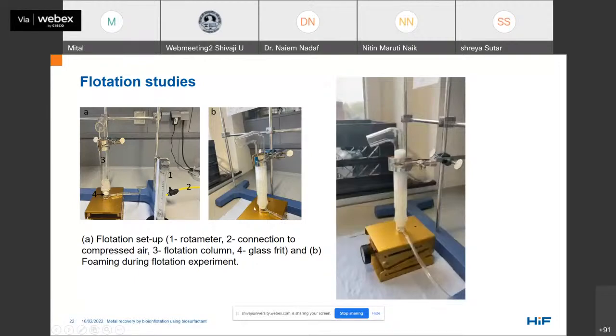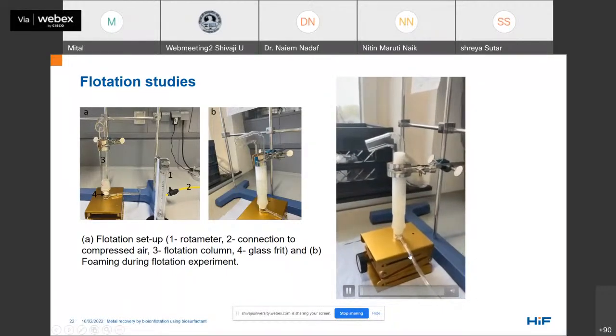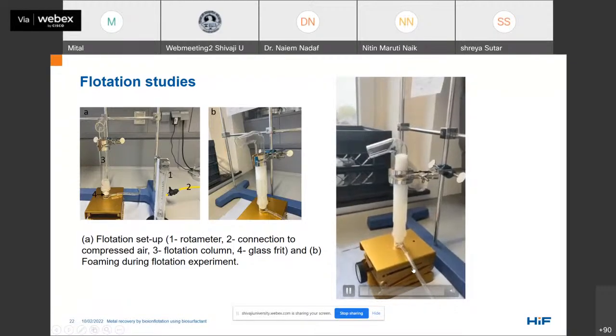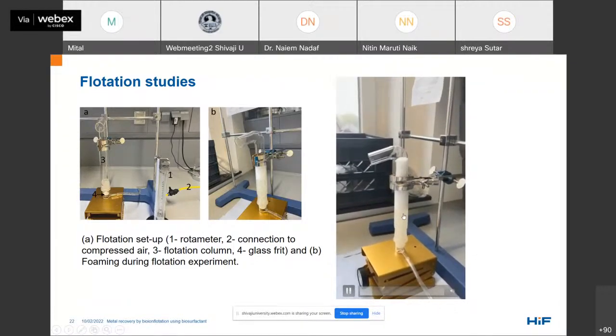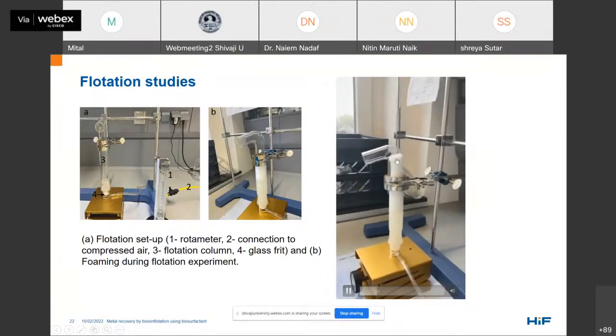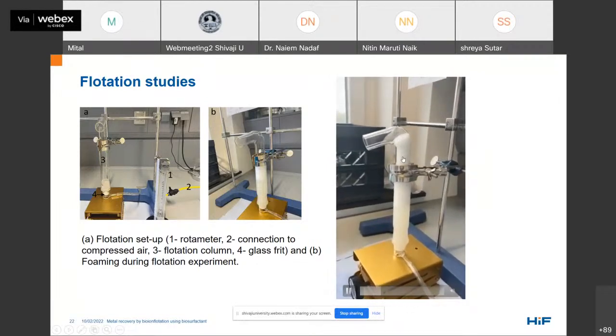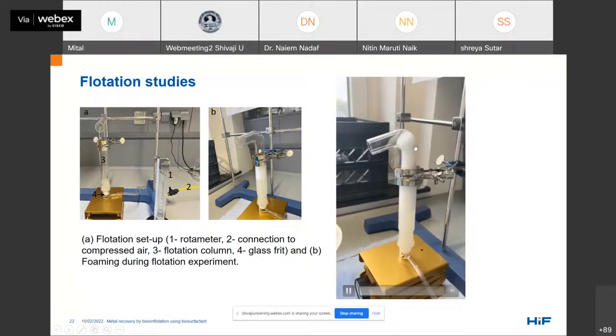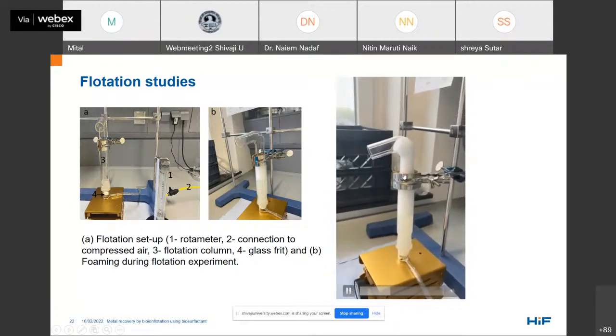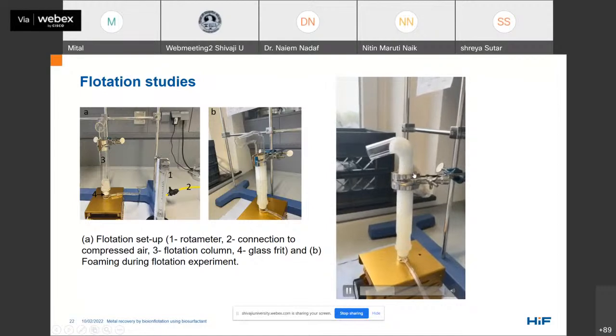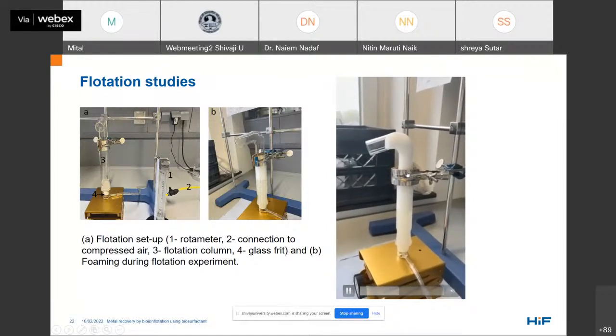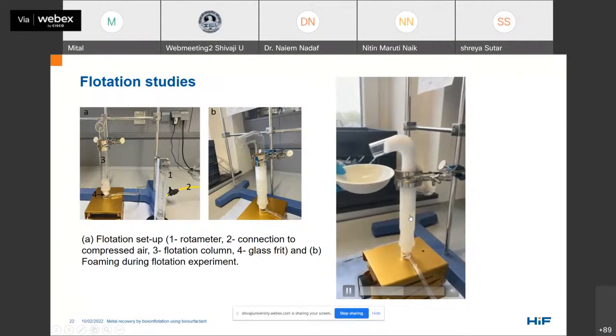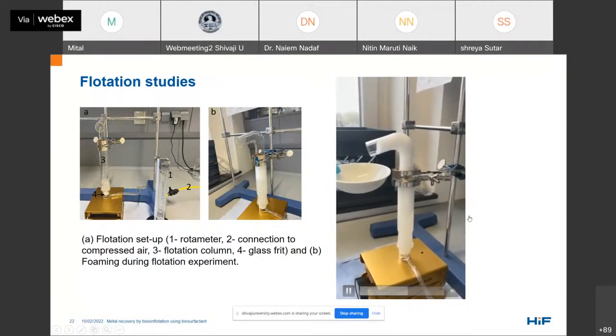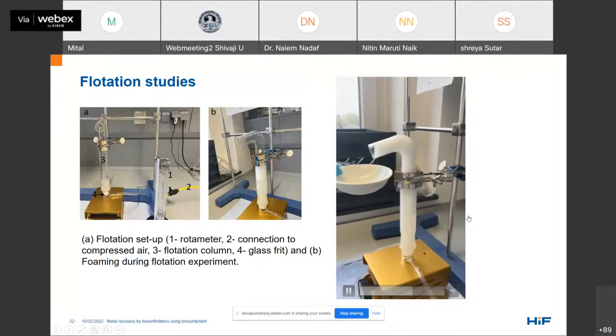So once you start the flotation, you can see the bubbles forming here and the foam increasing. So here is the video of the flotation experiment. Here you can see as the air increases, the foam is formed and it starts coming out of the flotation column. We usually collect this foam in evaporating dishes, and we change the evaporating dish every minute so that we have different concentrates, and we can calculate the kinetics of flotation from these different